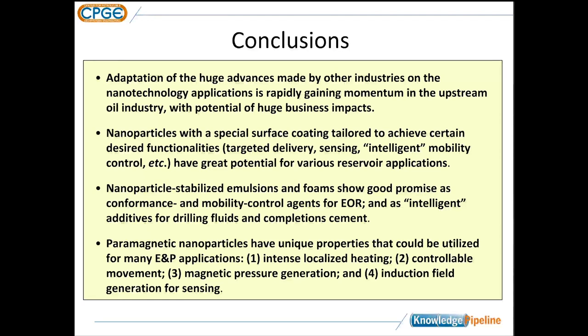I can add a little bit on that. Many of the surface coating materials are relatively moderate chain length polymers, and then ionic polymers, so that if there's any salinity, these ionic polymers respond to the surrounding salinity. Depending on the salinity, they can be either expanded or contracted or changed. So that's another factor why the hydrodynamic size depends on the salinity.